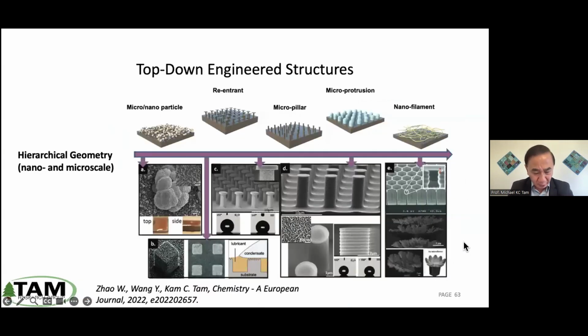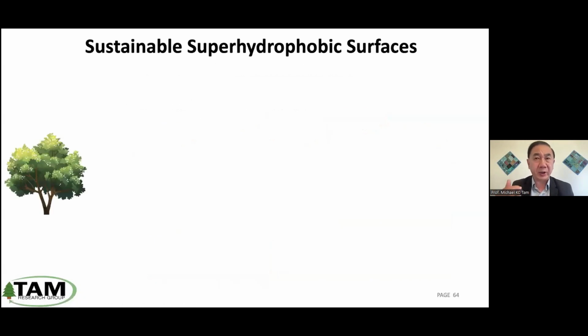So traditionally, what has been done is that they machine or make rough surfaces, micro nano structure surfaces, so that the surface is like a lotus leaf, super hydrophobic. So we reviewed this system, and then they surface coat or modify the surface, and then they're able to demonstrate that this surface is able to also capture water. However, our system is very much sustainable, and we use all materials from nature. So we use plants, and from plants you get